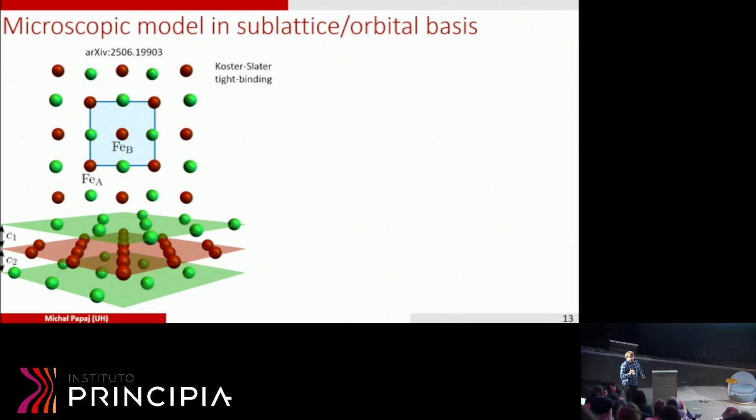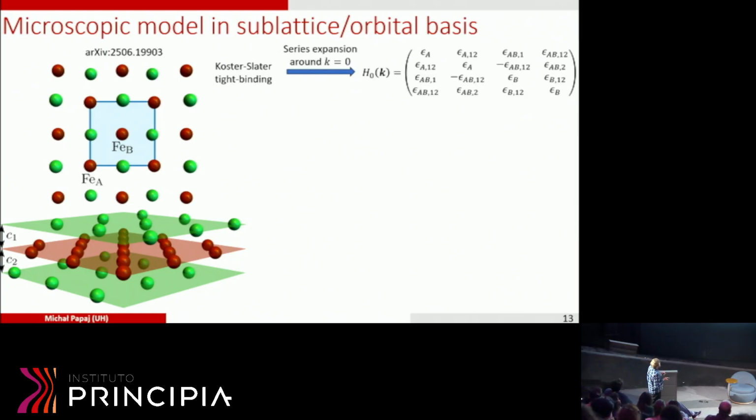But also the fact that this exfoliation process certainly does something to the material in the C direction, let's say, gives another hint that there may be something happening here. So we construct a model based on the 3d orbitals, dxz, dyz, dxy orbitals on the iron sublattices, and all 3p orbitals on the selenium sublattice, but then we integrate out all the selenium orbitals to get just an effective model in the dxz, dyz orbital space, because we want to limit the number of parameters.